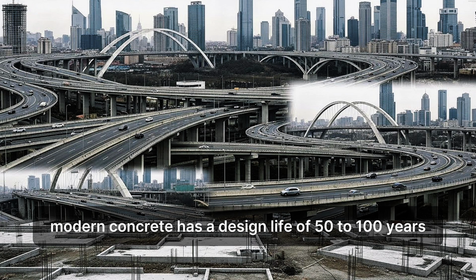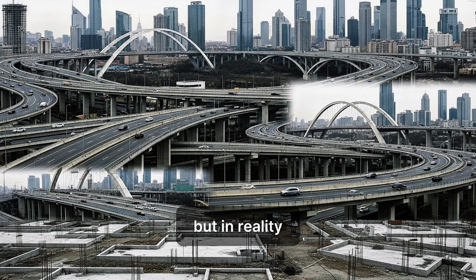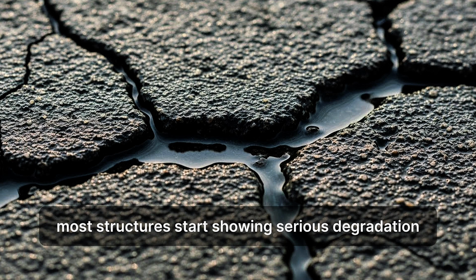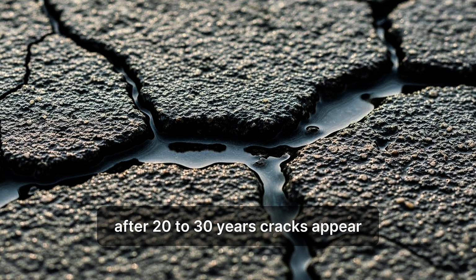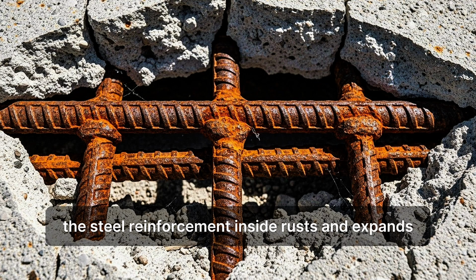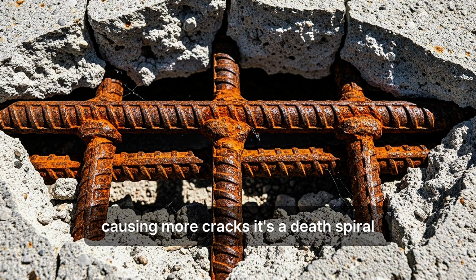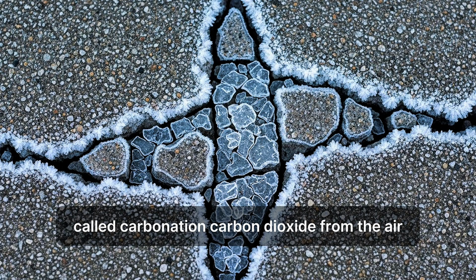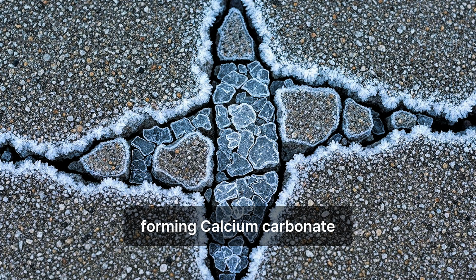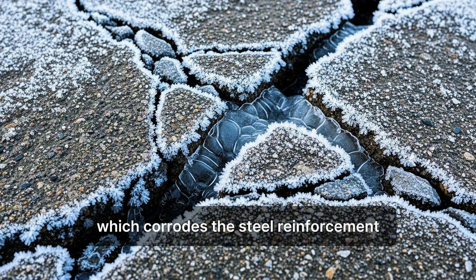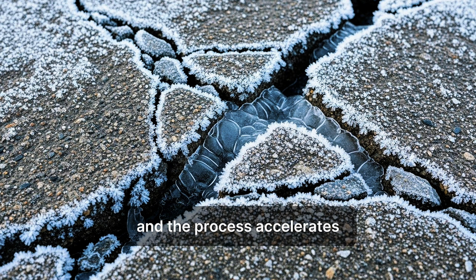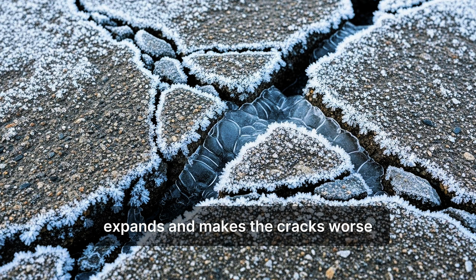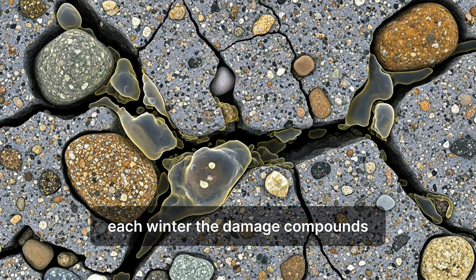Modern concrete has a design life of 50 to 100 years. But in reality, most structures start showing serious degradation after 20 to 30 years. Cracks appear, water seeps in, the steel reinforcement inside rusts and expands, causing more cracks. It's a death spiral. The primary culprit is a chemical reaction called carbonation. Carbon dioxide from the air reacts with calcium hydroxide in the concrete, forming calcium carbonate. This lowers the pH, which corrodes the steel reinforcement. Add salt from roads or seawater, and the process accelerates. Then there's freeze-thaw damage. Water gets into cracks, freezes, expands, and makes the cracks worse. Each winter, the damage compounds.